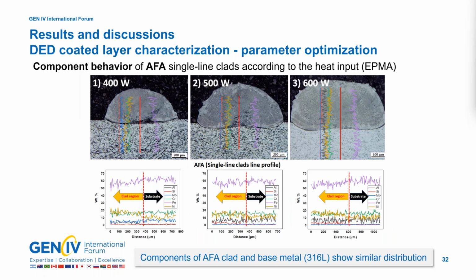To understand the component behavior of the single line bead, EPMA line analysis was performed. It was found that under all conditions, the composition distribution of AFA is similar to that of the substrate material 316L.